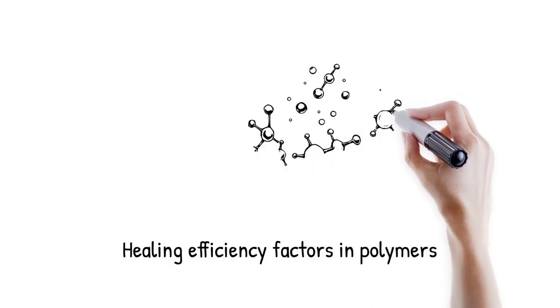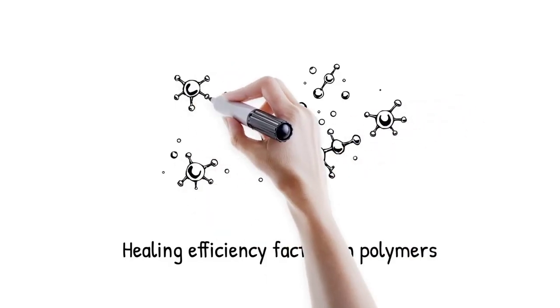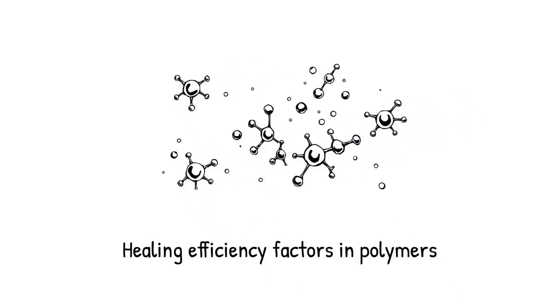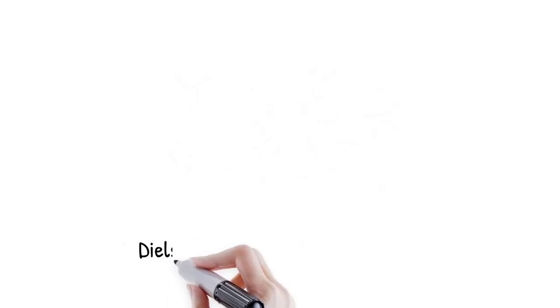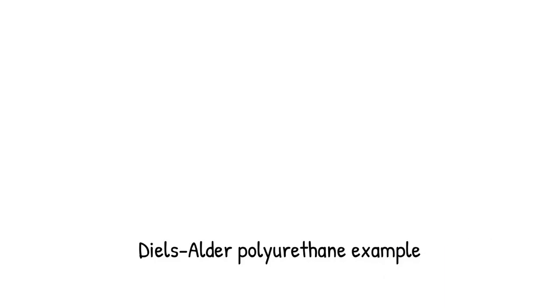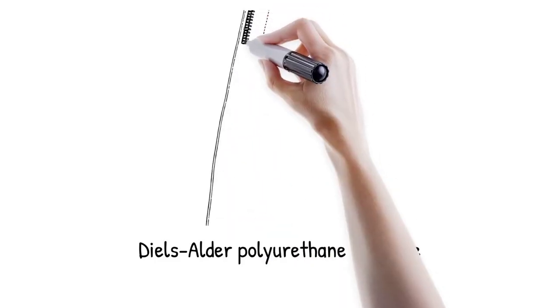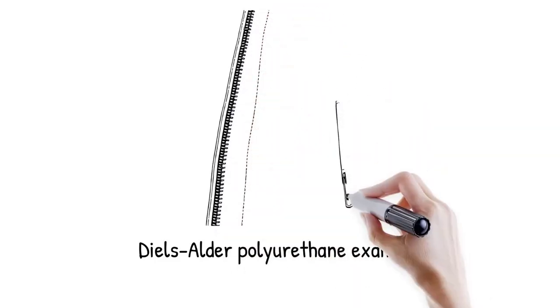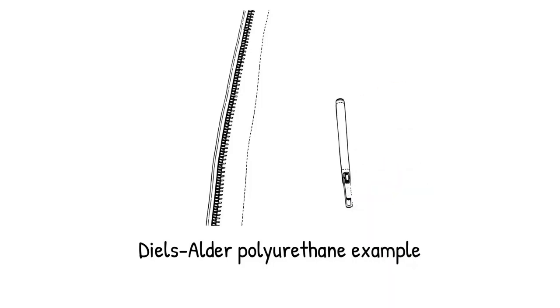The efficiency of healing depends on bond kinetics, network mobility, and catalyst presence. Such designs mimic biological repair by balancing bond breakage and reformation under environmental stimuli. A Diels-Alder-based polyurethane coating exposed to UV can recover 90% of its original toughness after a gentle heat treatment. It is like a zipper that unfastens under stress, but zips itself back up when you pull it again.